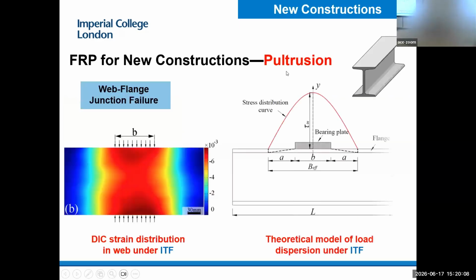So in order to figure out the mechanism, we use DIC, digital image correlation technology. You use two cameras to monitor the deformation of the material under loading, and you can work out the strain distribution on the surface of the material.